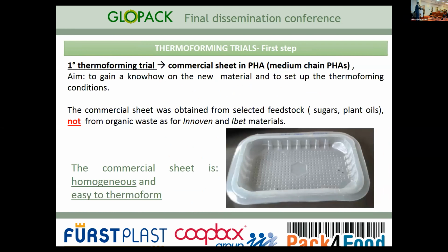We decided to schedule the thermoforming trials in different steps. We didn't have a very high knowledge about the PHA materials because it's not a standard commercial material used for food packaging, so we decided to go on in different steps. The first step was to obtain some knowledge about this material. So we started thermoforming some commercial sheet that was on the market, made from PHA with a medium chain length. These materials are not coming from food waste, but from selected feedstocks like sugars or plant oils. So it's something commercial, and it's quite different from the material that we want to use inside our project, the material coming from food waste, like the one provided by Innoven and others.